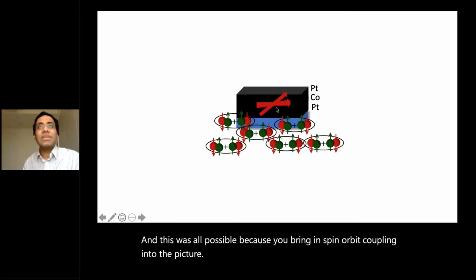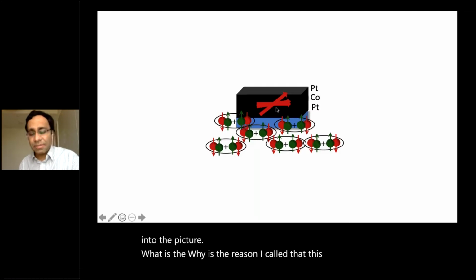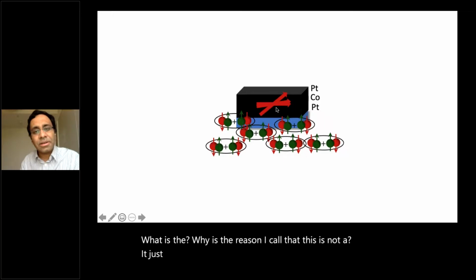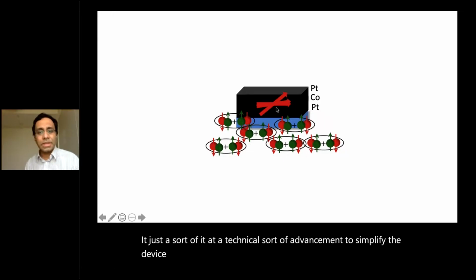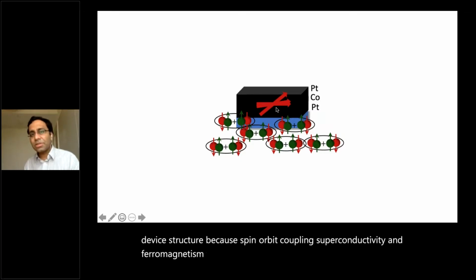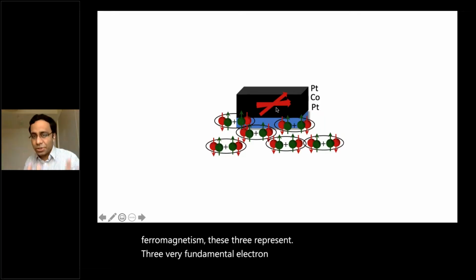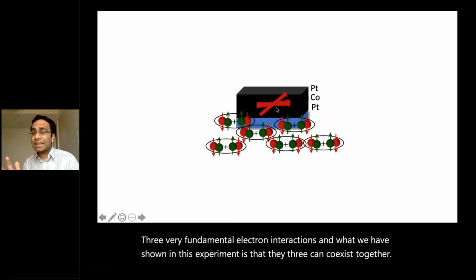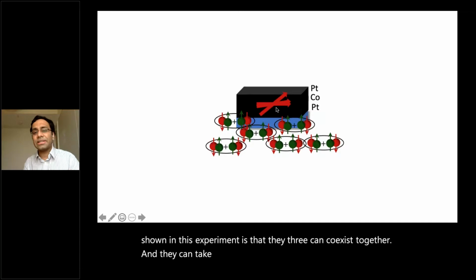The reason I say that this is not just a technical advancement to simplify the device structure is because spin orbit coupling, superconductivity, and ferromagnetism, these three represent three very fundamental electron interactions. And what we have shown in this experiment is that the three can coexist together, and they can take part in generating this very novel form of superconductivity, that is triplet superconductivity.